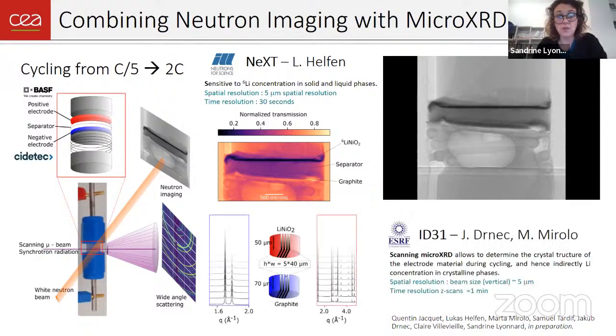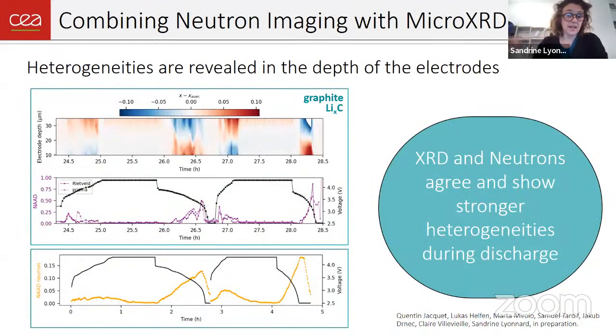And so we combine that with the XRD, and the experiment is consisting in doing very fast vertical scans of your battery with a small beam at different locations, going through the full cell, so the two electrodes, with a beam that is 5 microns in height and a time resolution that is roughly 1 minute. And with this experiment, of course, you get the diffraction patterns of both materials, and you can have an idea of the different phases, the state of lithiation of your electrodes. So you elaborate this data quantitatively, and this is the kind of result that you get.